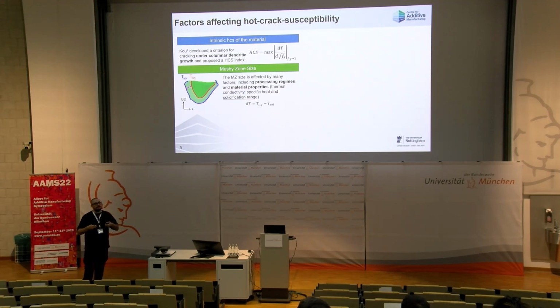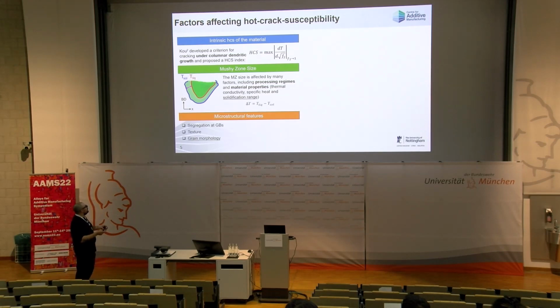So you have a higher chance to nucleate hot cracks in these regimes. But as far as material is concerned, we can try to map this just with solidification range. And then, of course, there are microstructural features such as segregation, grain boundaries, texture, and grain morphology, which we all know acts on hot cracking.